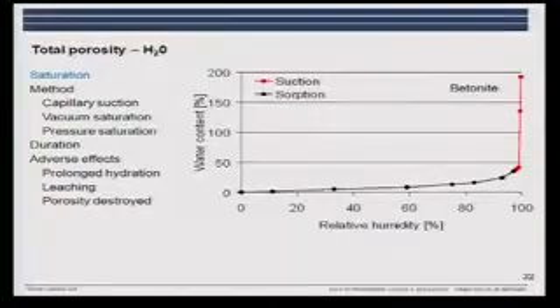The graph, I'll take that first. The illustration here is for bentonite. That's why we have this huge amount of water and a desorption isotherm which is quite different from what you see. We used bentonite to intermix with cement to decrease the clinker factor in some samples. When we were mixing the bentonite in, we needed to know how much water would be absorbed in the bentonite and when it would be released during hydration, for instance. So that's why we did this.